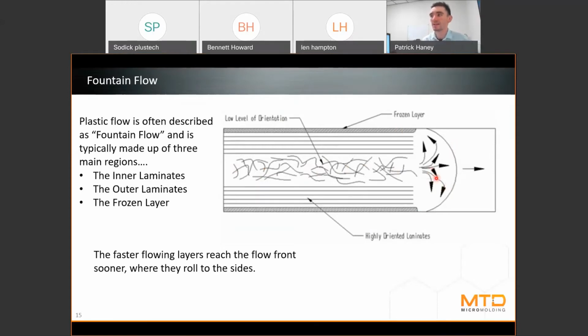So the dynamics of fountain flow are made up of three main regions, right? The inner laminates experience the lowest amount of shear, therefore the lowest level of orientation, but they experience the highest speed or the highest degree of velocity because they experience a lesser amount of frictional drag. Okay, the outer laminates tend to have lower speeds because they experience more frictional drag, yet higher orientation for the same reason. Okay, and then there's a third region called the frozen layer.